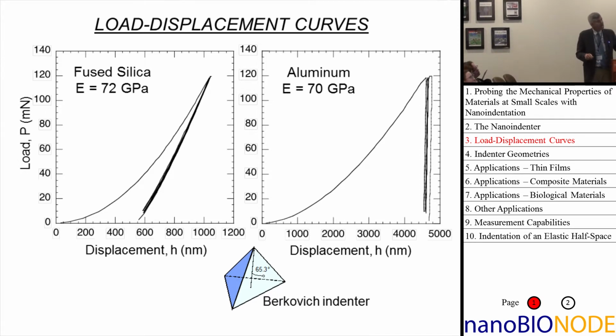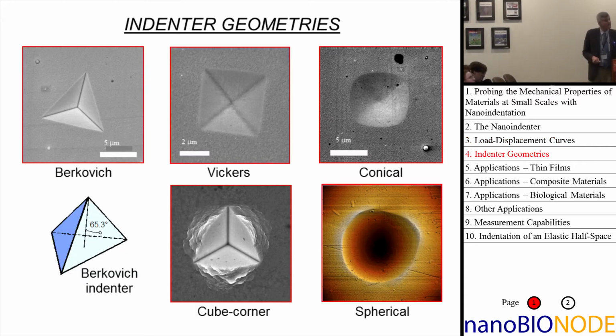And so, this is actually a fairly big nano indentation. It's made to 1,000 nanometers. We can do this same thing easily at 100 nanometers, and with a lot of trouble, you can do these things down at the 10 nanometer scale, but you have to be extremely careful when you get down there. I'm often asked, what's the smallest nano indentation that you're comfortable making and taking property measurements from? And the answer is that in the systems I work with, about 50 nanometers. I don't really want to work below 50 nanometers. Life gets too messy. Lots of issues there, so we don't need to talk about that.